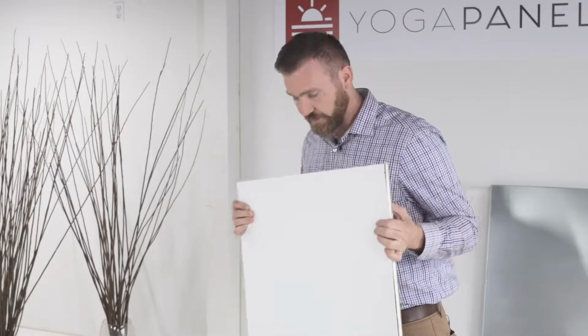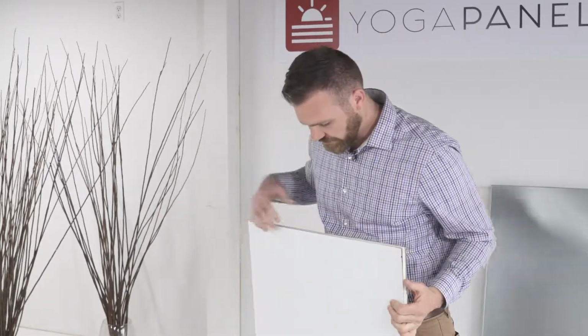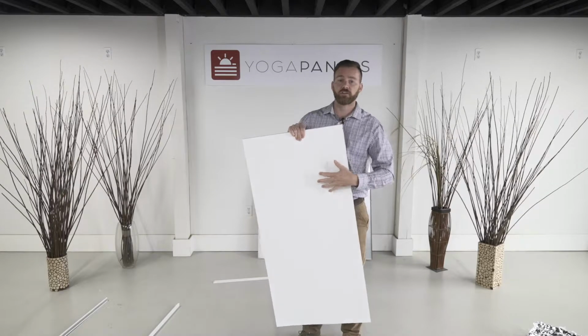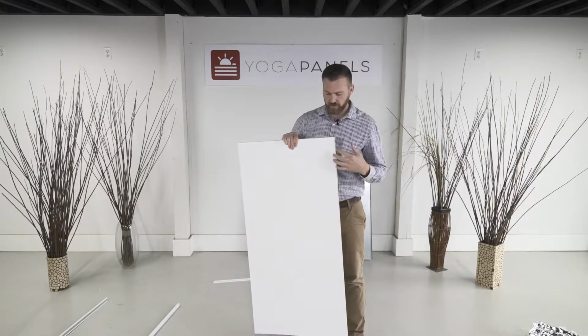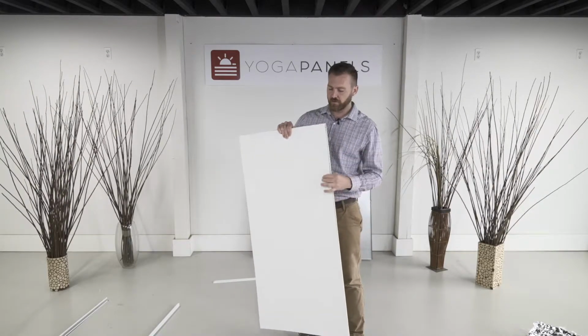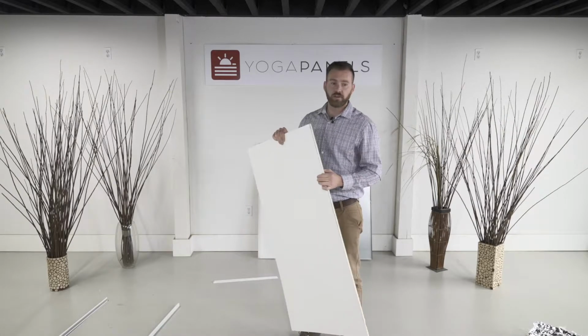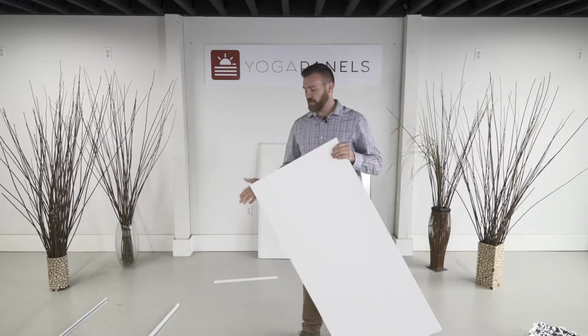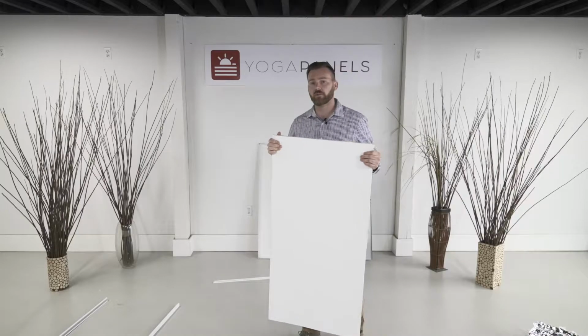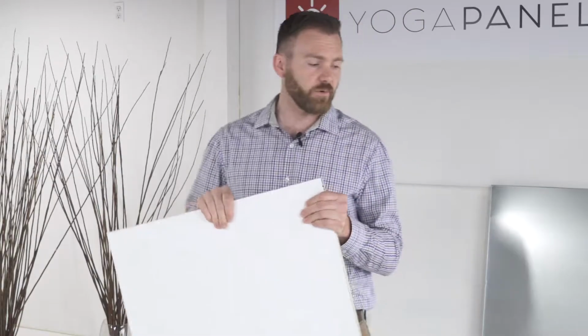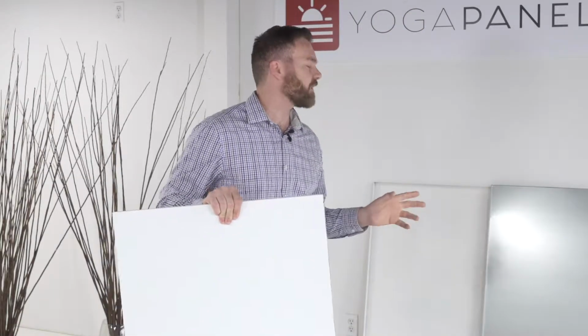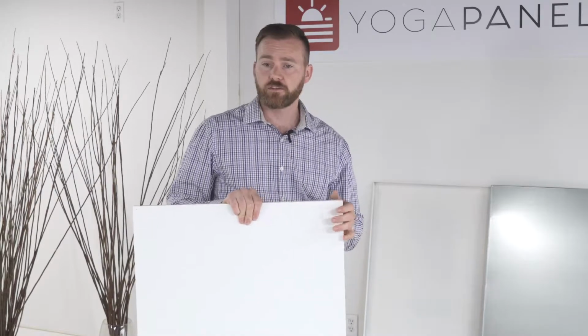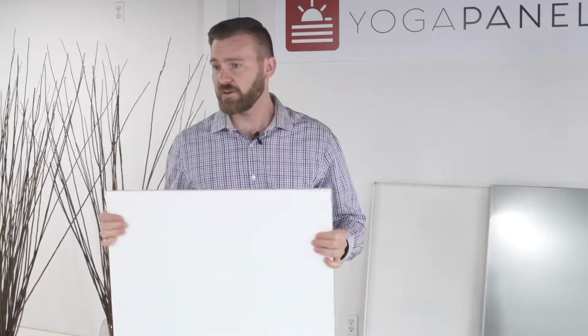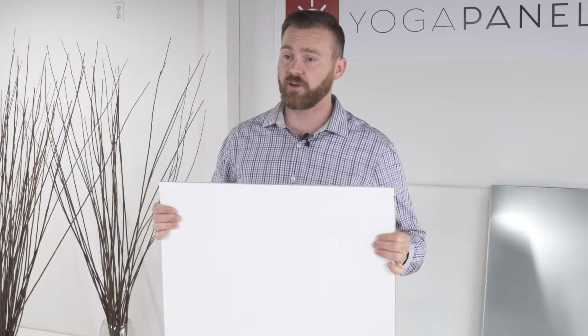So that's the major difference. Here you have a complete carbon fiber infrared panel. You're not going to lose any inefficiency with the heating core. It's a lot thicker, it's more durable. The shelf life for a carbon fiber element is around 200,000 hours, whereas the shelf life for the Marley Go Anywhere panel ranges about 8 to 10,000 hours. So while 8 to 10,000 is a long time, it's nowhere near the run life of a carbon fiber panel.